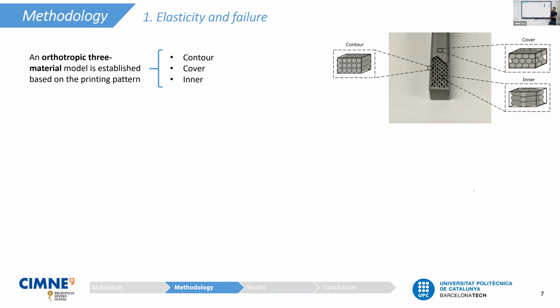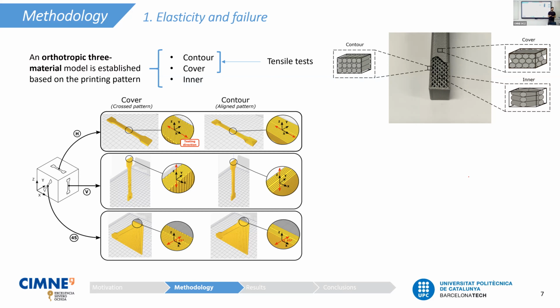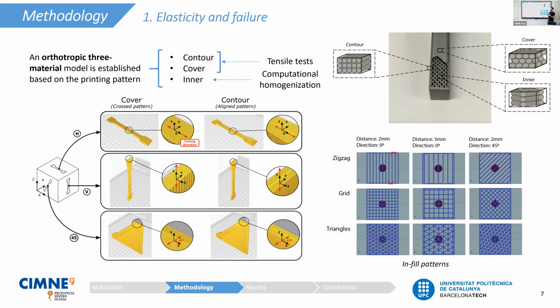So the first two, the contour and cover zones, are characterized via tensile tests. Since each of these printing patterns behaves orthotropically, we characterize each material direction independently. And then for the inner part, since there are several printing patterns that can exist, such as zigzag, grid, triangles, and within every printing pattern we can see different infill densities, it is extremely expensive and useless to characterize this printing pattern via experimental tests. Therefore, the approach we are following is a computational characterization.